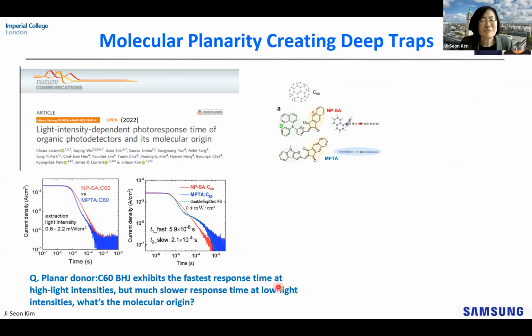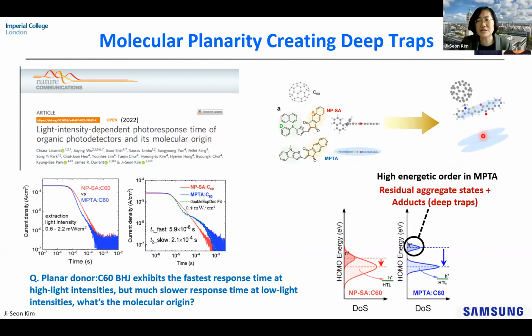So making planar and rigid molecules is really good for photo conversion devices. Now, we have to be quite careful. When we make a rigid and planar structure, of course, the molecule has a tendency to have very strong intermolecular interaction. And also, if you use a planar molecule without bulky side groups in the blend with, for example, C60, it can also form an adduct structure.